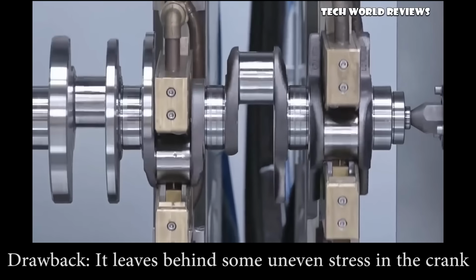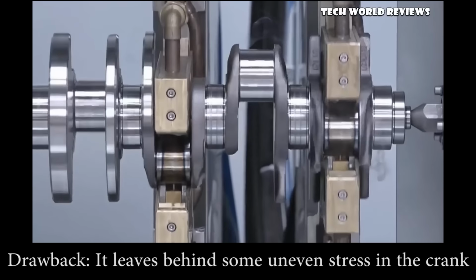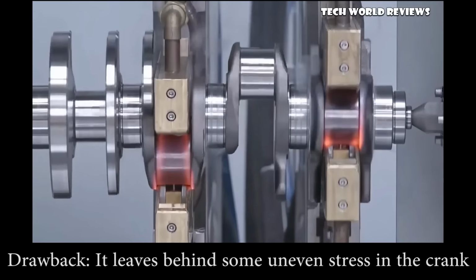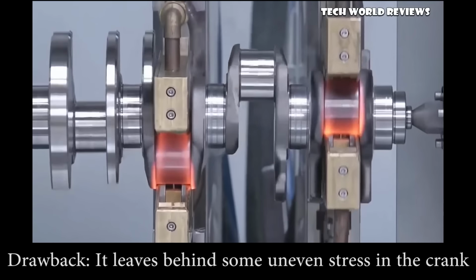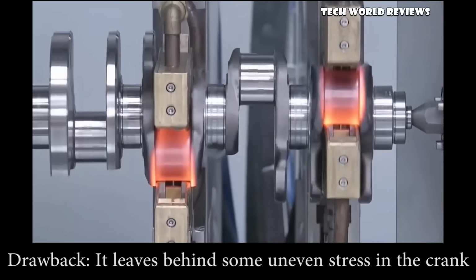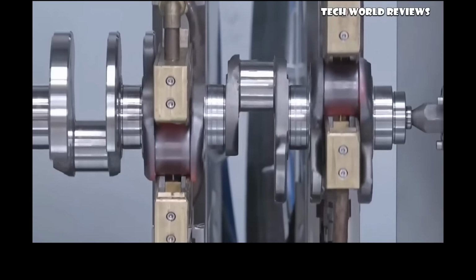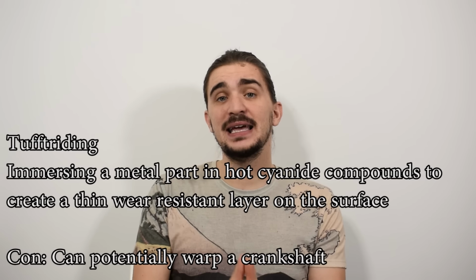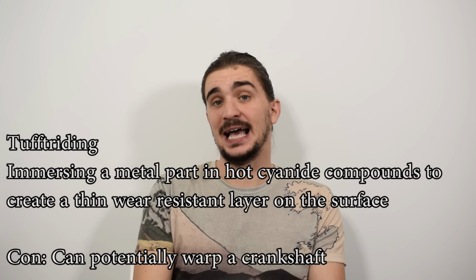And while it's more than adequate for most OEM and even performance applications, it does have a drawback in the sense that it doesn't heat up the entire surface of the crank evenly, which leaves behind some uneven stress areas in the crankshaft. And this is why extreme racing applications often rely on more advanced surface treatments such as tuftriding or nitriding. Tuftriding immerses the crankshaft in hot cyanide compounds.